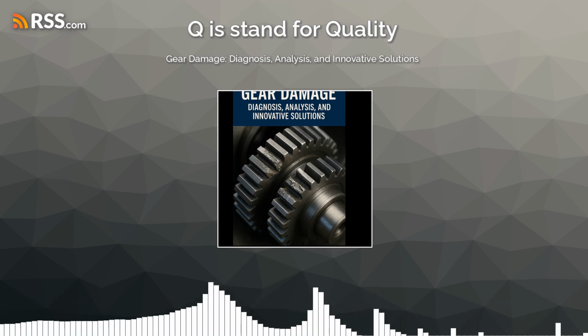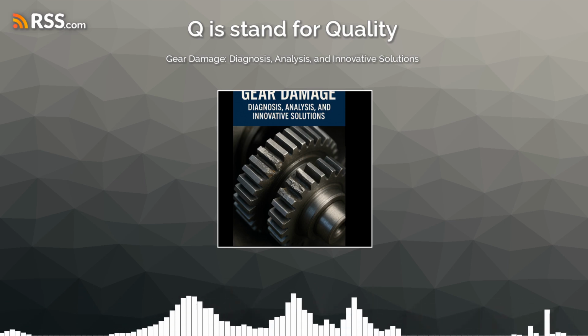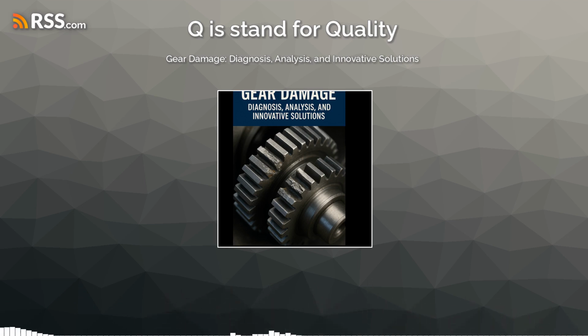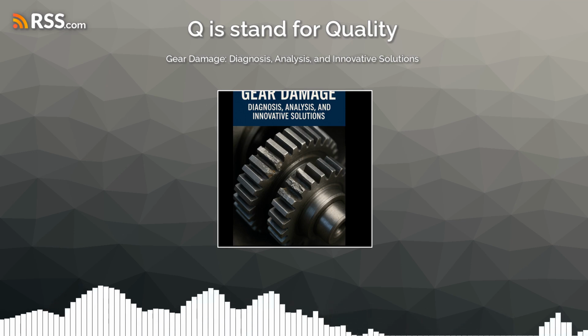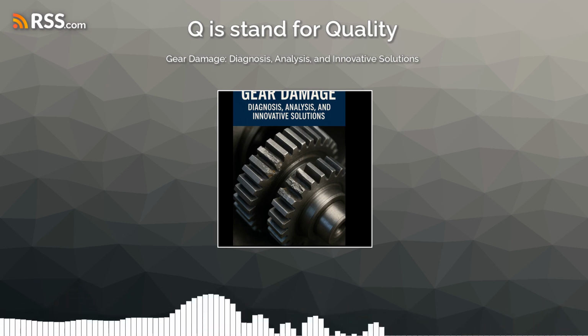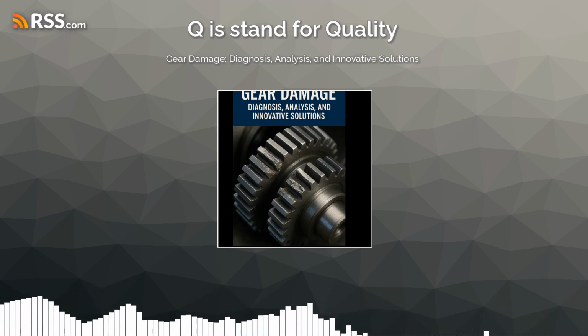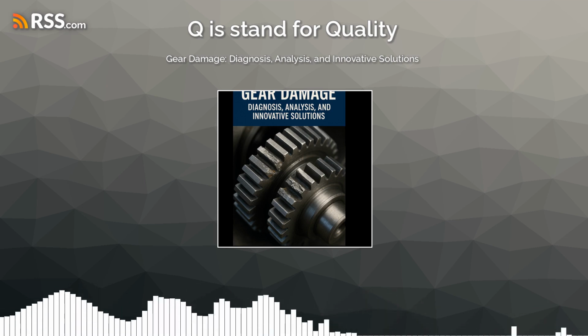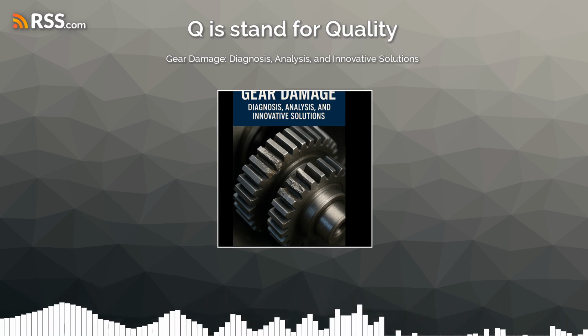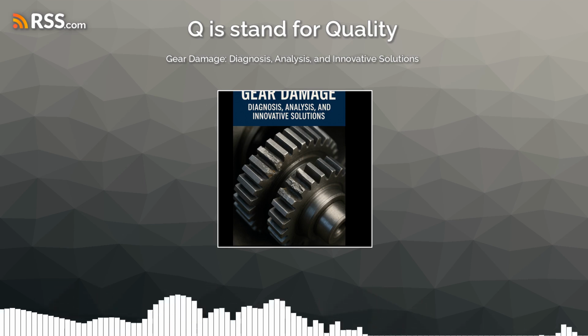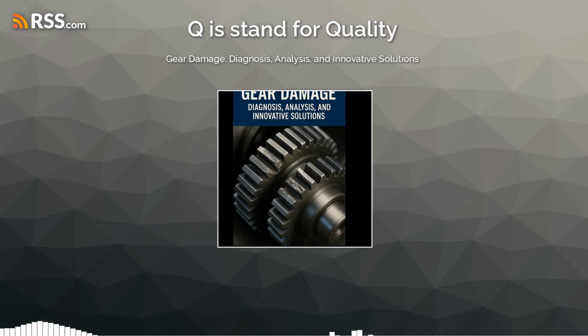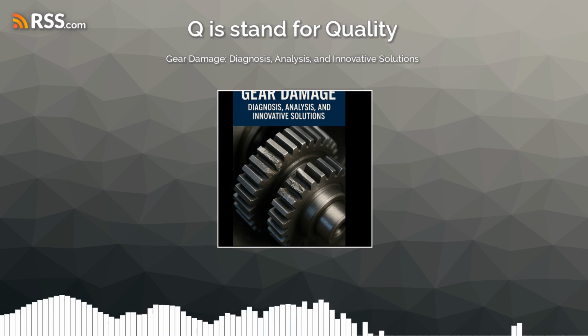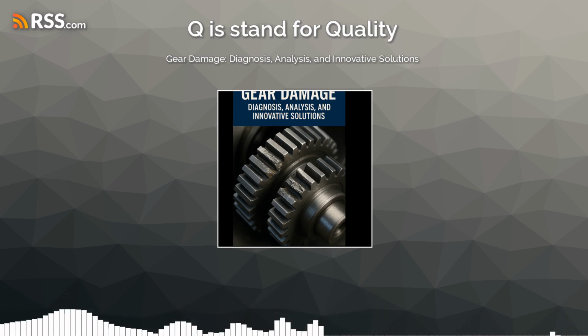So how do engineers fight back? How can we improve polymer gear performance and make them more resistant to wear and heat? Several key strategies. Reinforcement is a big one. Adding glass or carbon fibers into the polymer matrix makes a huge difference. How? The fibers are much stronger and stiffer than the polymer, and they conduct heat better. It creates a composite material. This can increase load capacity by up to 50%. The fibers help distribute load and dissipate heat more effectively.